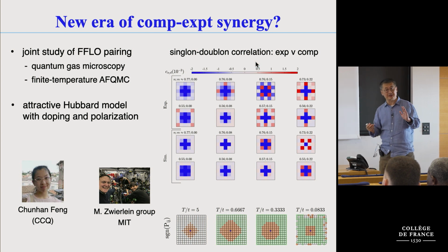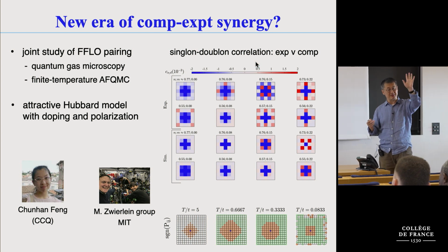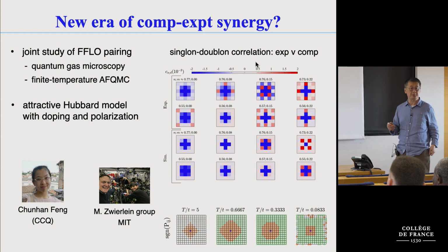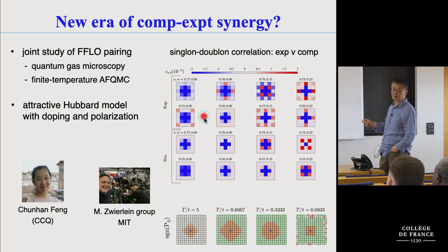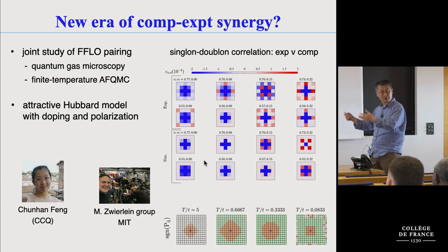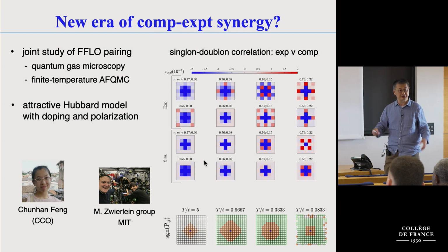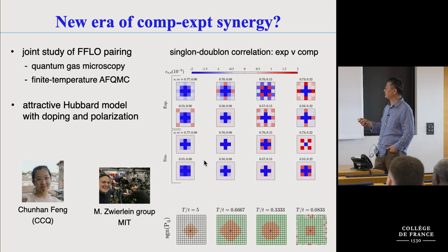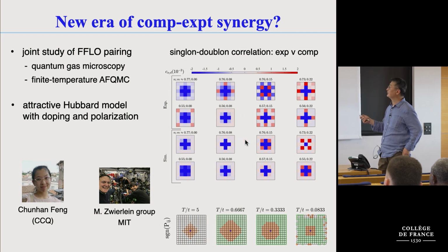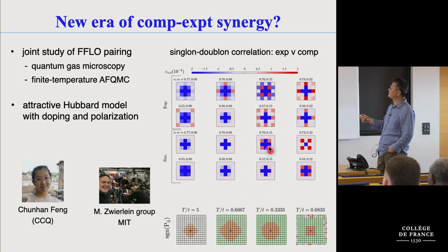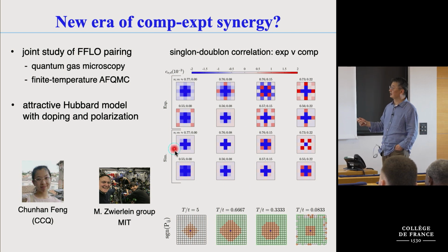So the setting is now that you imagine there's a magnetic field that polarizes the system, although in experiment it's not a magnetic field, it can just be polarized. So we have a negative U Hubbard model, which if it's not polarized would be more like the case that Tariq talked about. It's a sign problem-free exact calculation we could do. But now with polarization, it has a sign problem, so it's AFQMC. And here's experimentally measured singlon, doublon correlation, and the bottom two panels are theory, and you can see there's quite good agreement.